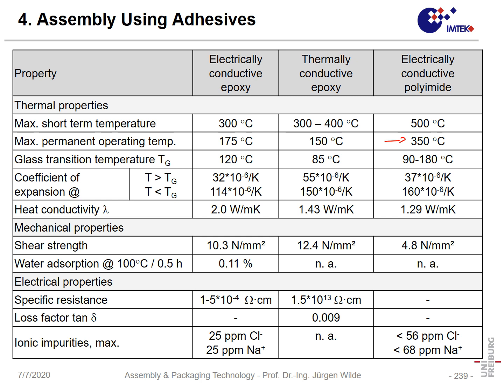Typically, the silver material here has a thermal conductivity of 2 watt per meter Kelvin. That's a factor of 10 worse, or even a factor of 20 compared to solder alloys. The adhesives which are filled with alumina have an even lower thermal conductivity. What is given here is some shear strength, 10 Newton per square millimeter or megapascal. That is not too high, but it is sufficient for almost all applications.